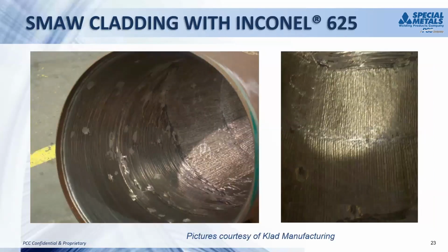Shielded metal arc cladding with Inconel 625 is still done commonly, particularly on elbows and different pipes that have an odd shape to them, where it may not be practical to reach in with a MIG system or a TIG system. One of the other things that's not really thought about, where the shielded metal comes as a big advantage, if you notice on this picture on the left, is a very thin-walled steel type tube. It's probably only about 3/8 of an inch thick.